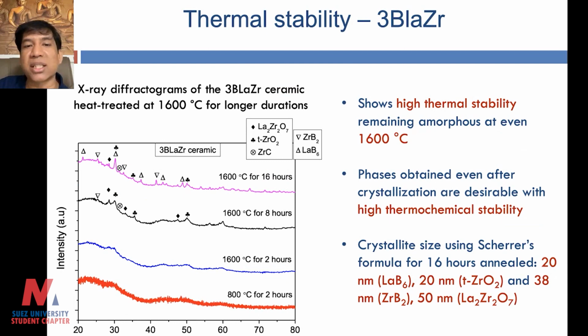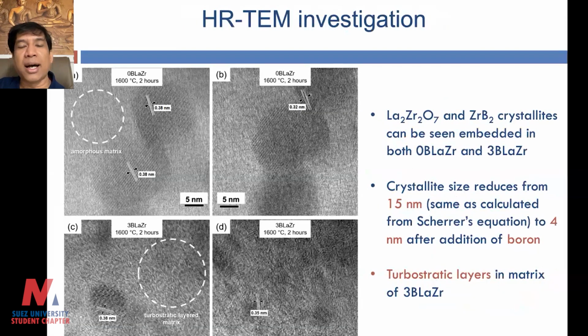For example, here it is shown to exhibit nanocrystals, but extremely small, fine nanocrystals of, say, lanthanum-based zirconate or zirconium boride when they were exposed to 1600 degrees Celsius for about 16 hours. So this is what we want. We want materials which can be very stable. Of course, we could have tested beyond 1600. We had some difficulties going beyond 1600 degrees Celsius because operating furnaces beyond 1800 is also a challenge, and therefore we are restricting the studies to 1600 as of now.